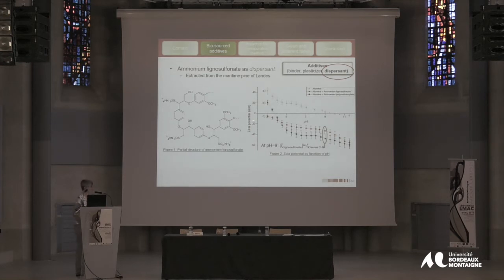So what we've done is simply replace this Darvan by lignosulfonate dispersant, which is in fact extracted from the maritime pine of Landes, very close to here, which has here the chemical formula with some ammonium ions. And again, what is interesting is that we managed to obtain a zeta potential which is close to minus 40, so very good for obtaining a good dispersion of the alumina.